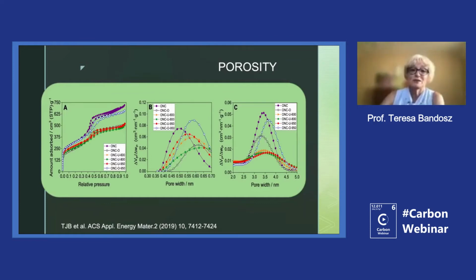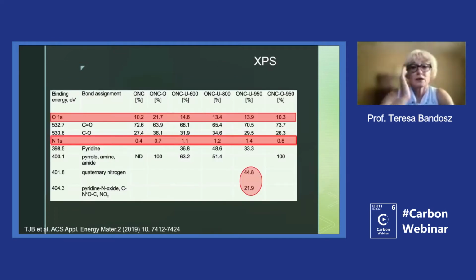But for carbons, it is really hard to distinguish and determine that effect. So we thought that what would be important is, of course, which carbon has the smallest pore sizes, and what is the spread of the distribution. So where is the maximum of the distribution in ultra micropores? Here you can see that ONC, which is the initial carbon without any nitrogen, has the smallest pores, and then we have the carbon modified with urea. And of course, we did that modification to introduce nitrogen.